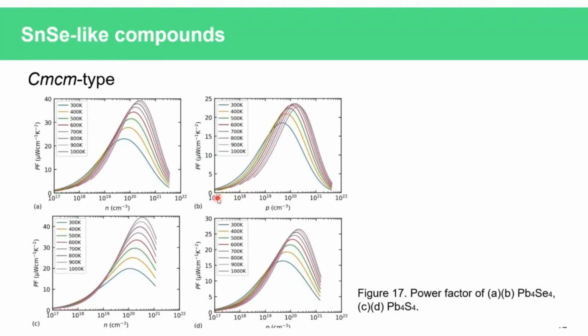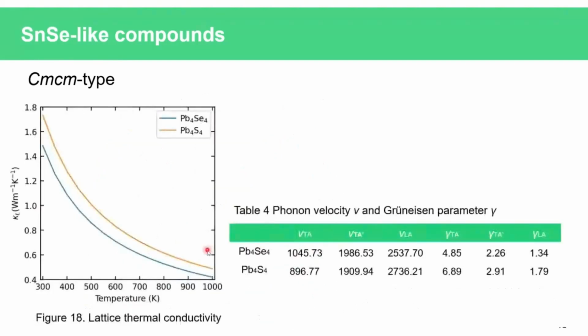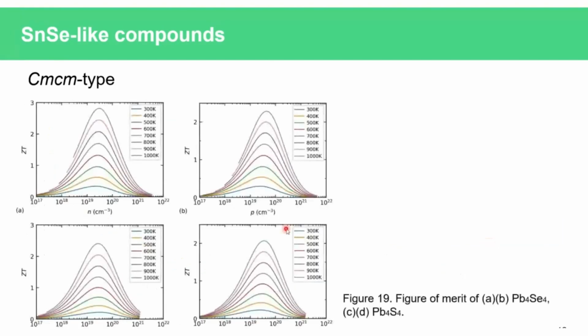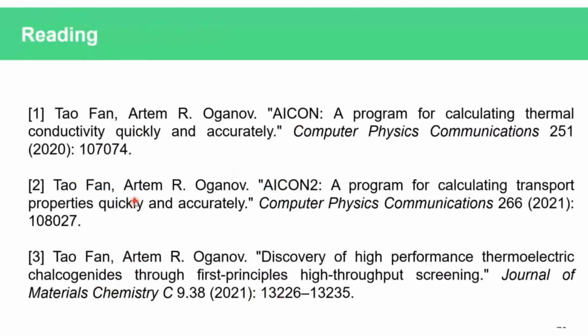For these 2 compounds, both N-type and P-type thermal power factor are high. Their lattice thermal conductivity, although not as low as the alpha phase, is still very low, mainly due to their low phonon velocity and large Grüneisen parameter. Here shows these 2 compounds' figure of merit. So both compounds are excellent N-type and P-type thermoelectric materials.